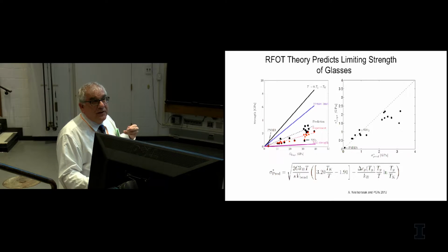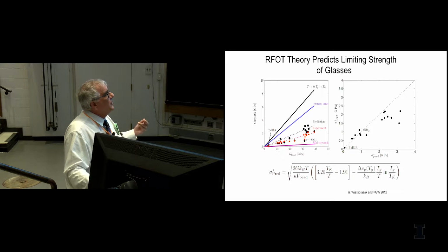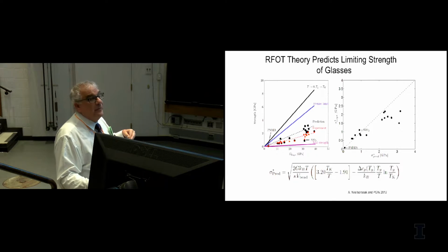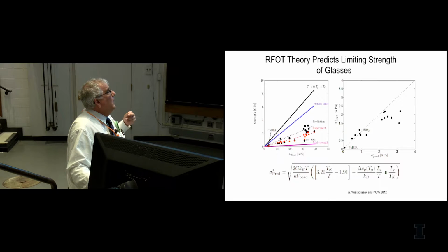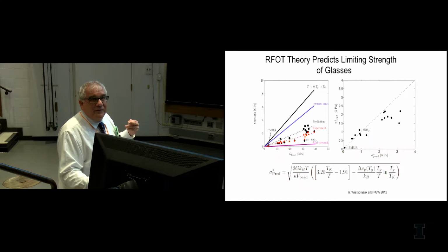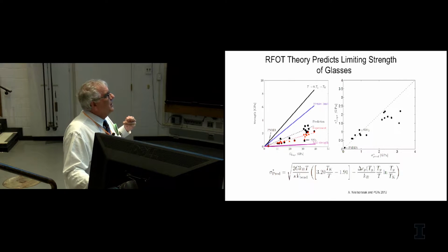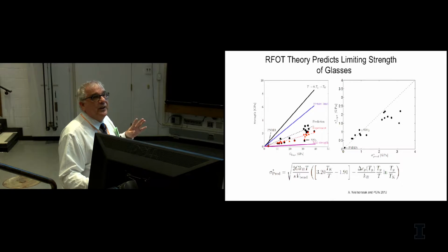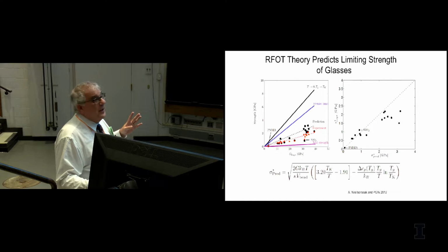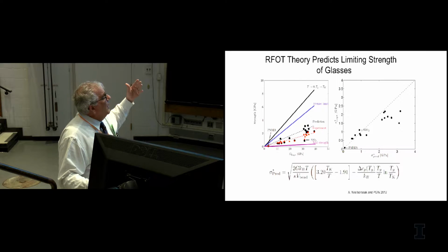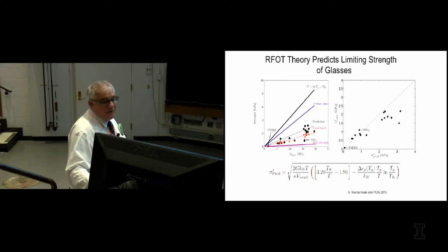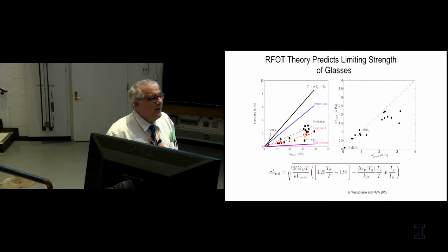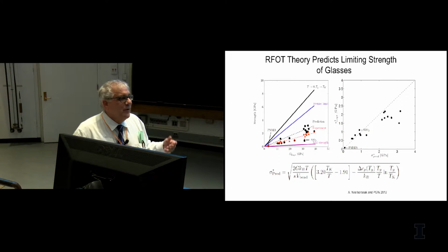If we could make glasses on much longer time scales, we could lower the glass transition temperature and we could make much stronger glasses. This is not very possible for the reasons I just said in a direct way of making glasses, but it is possible to get lower energy glasses by a vapor deposition process. And one can get basically glasses that are about twice as strong, we think, as the glasses we have today. The problem is, of course, making anything by vapor deposition is very expensive and probably only good for coating your glasses, so they won't scratch.